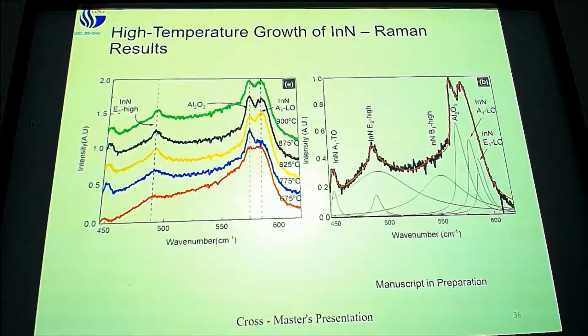So going to higher temperature, we actually do grow indium nitride. We tried growing it at 900 degrees Celsius, 875, 825, 775, and 675. All of these temperatures are above that 600 to 650 degrees Celsius decomposition temperature. Now, word to the wise, this is a very low growth rate. That means our growth rate is just slightly above the decomposition rate at this point. So we're only talking about 45 to 55 nanometers of material for these samples, which is part of the reason they're noisy in the Raman.